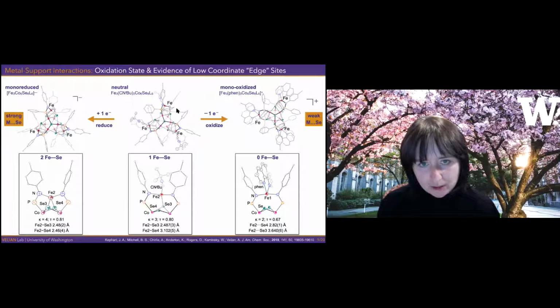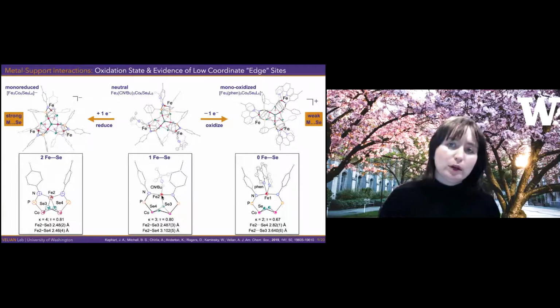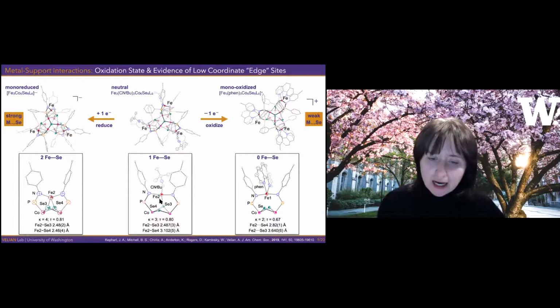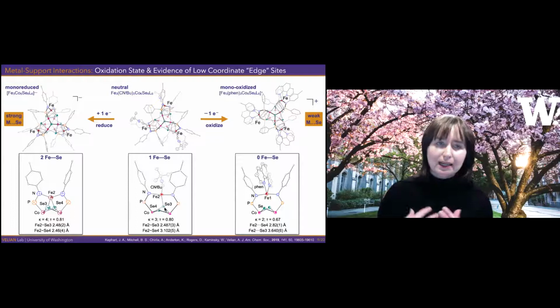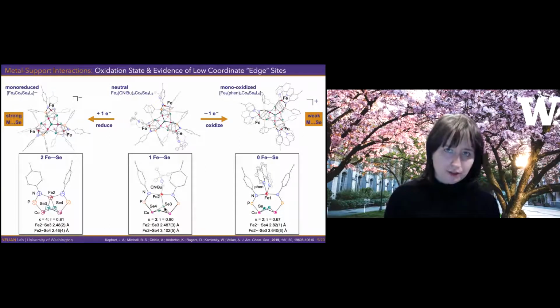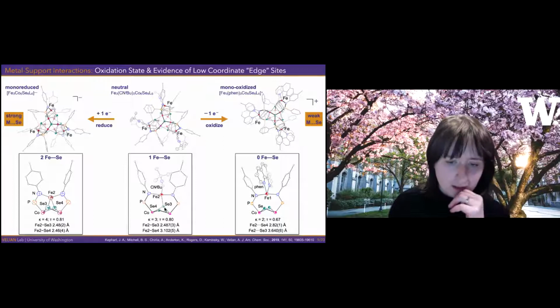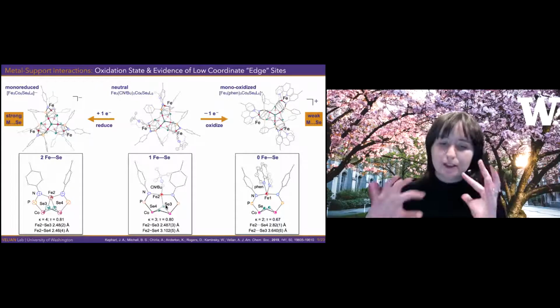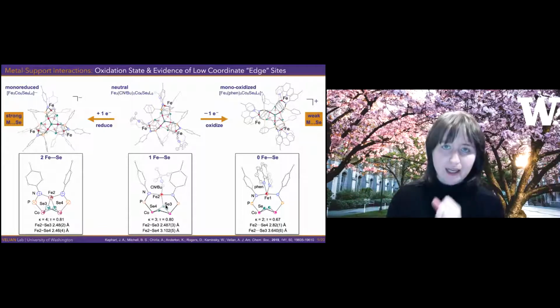Okay, so it's a snapshot of this one site. The iron is anchored to the cluster by 2 amides that have been deprotonated, aminophosphines. Here they are. What was really cool when we got this first structure was to see that there is indeed an interaction between the iron and the selenium core, because we really wanted to emulate that. We were aiming for a hemi-labile interaction between the metal and the cluster, going back to this idea of low coordinate sites that are active sites in catalysis.